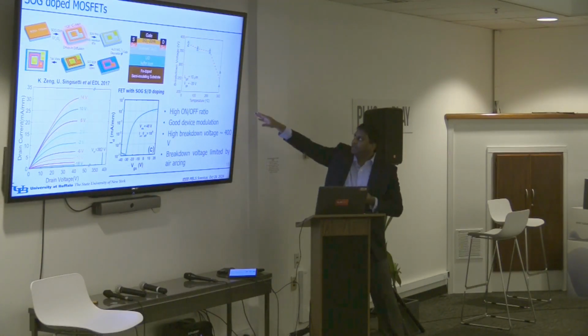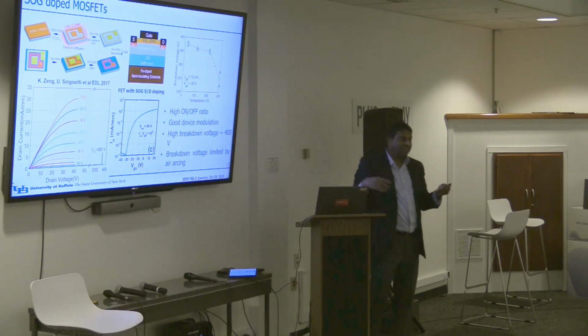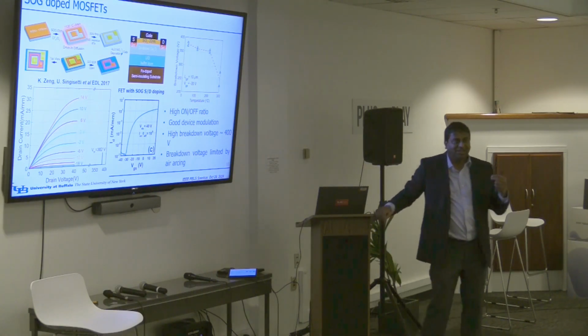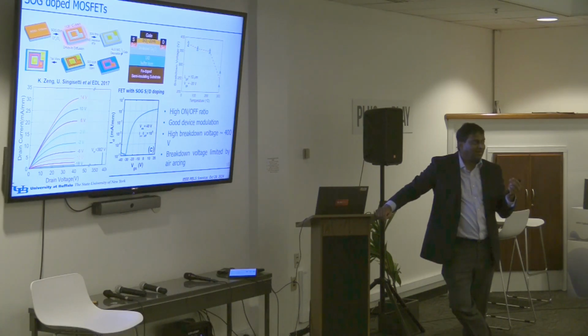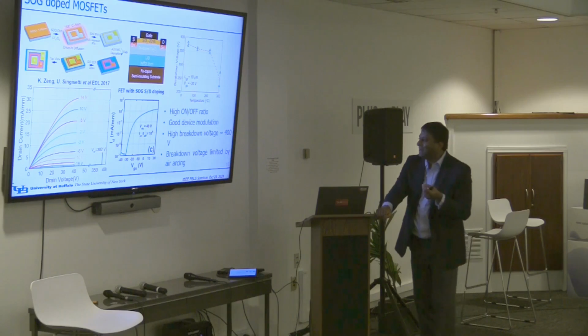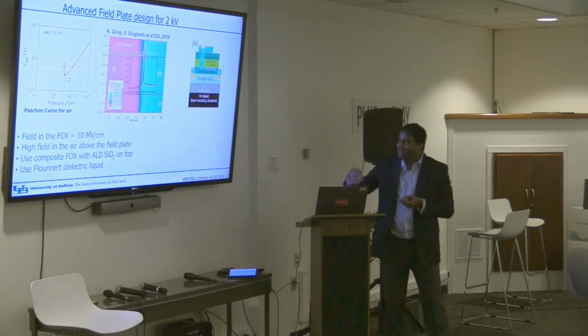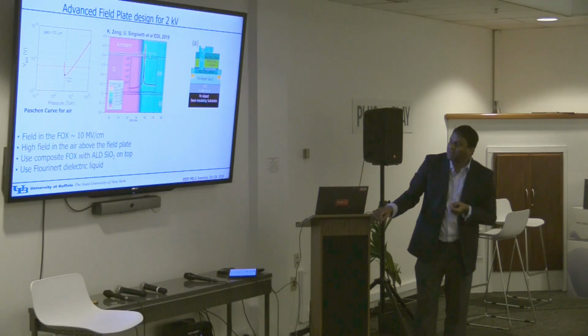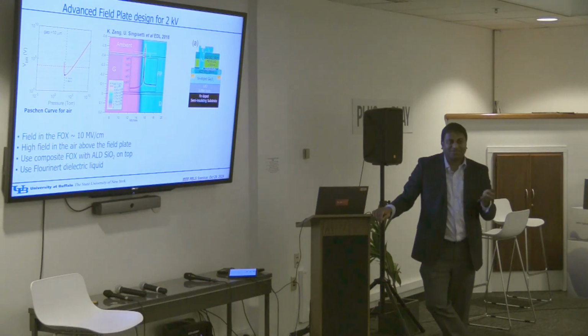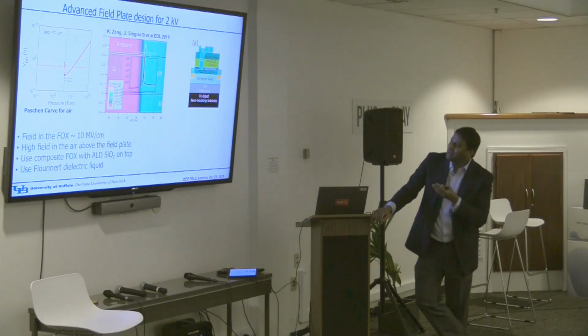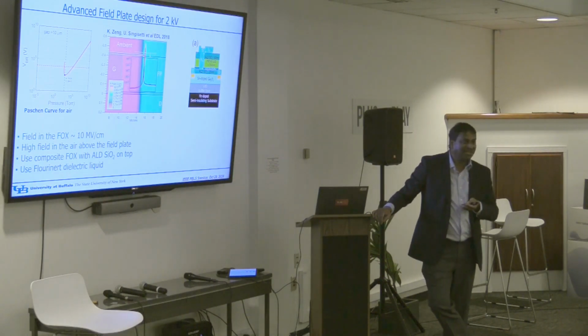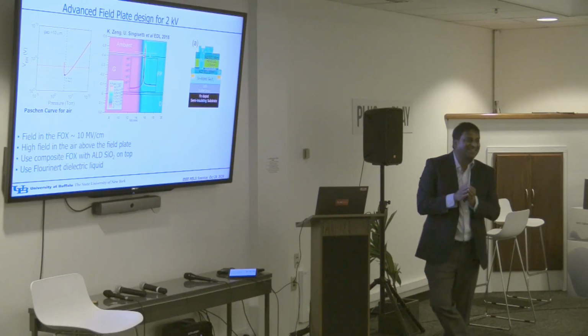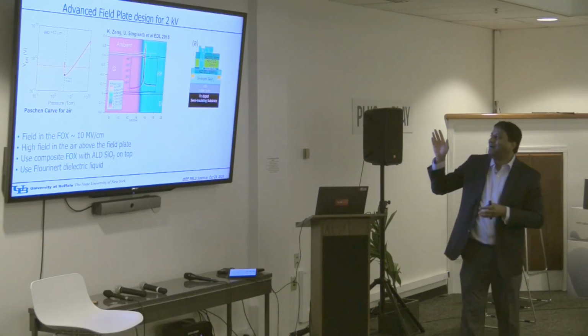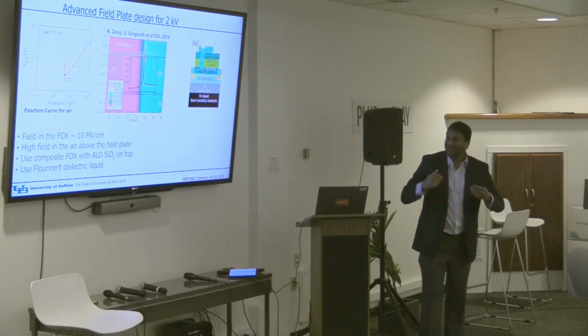And you can see it's decreasing with temperature. Now the student, when he was measuring this on our manual probe station, when it breaks down, he could actually smell the ozone coming out, right? You could see the spark coming out. So he said, okay, this is air arcing, it's not the device breaking. This is kind of interesting. And then he did some modeling, and you can see on the left here, the air breakdown curves, using the dimensions we use. You got 384 volts, you got 382 volts. I'm surprised at such a coincidence of the value, but clearly air breakdown was happening, right?